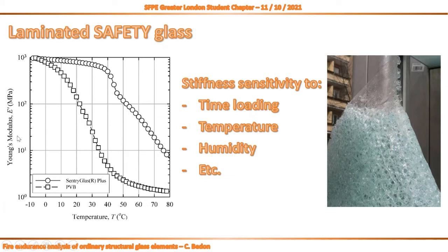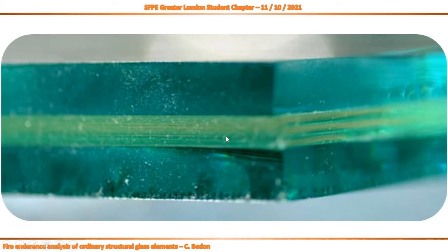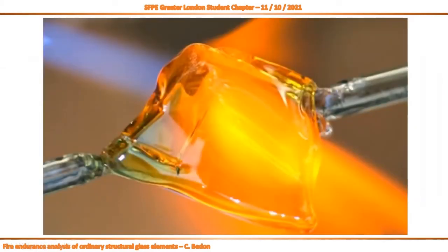In this chart, you can easily see what happens to the elastic stiffness of our bonding layers. The typical solutions in use are PVB or SentryGlas. As a function of temperature, you can see that the nominal value in design conditions is strongly affected by the operational temperature. But this is not the only influencing parameter. We will see that a combination of unsafe operational conditions can affect the shear stiffness of these bonding foils. But more or less, we have the instruments and tools to take care of this aspect and design structural glass at room temperature for most of the boundary conditions of interest.